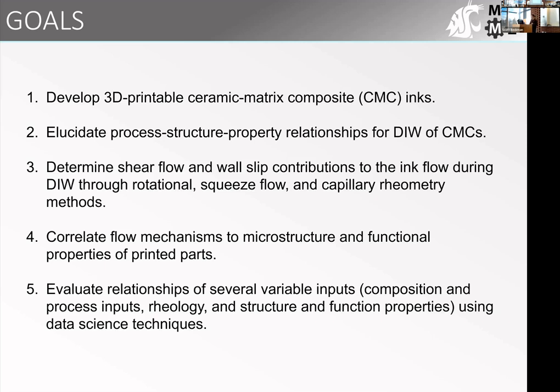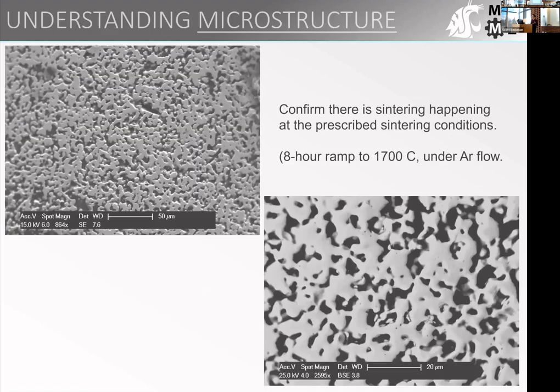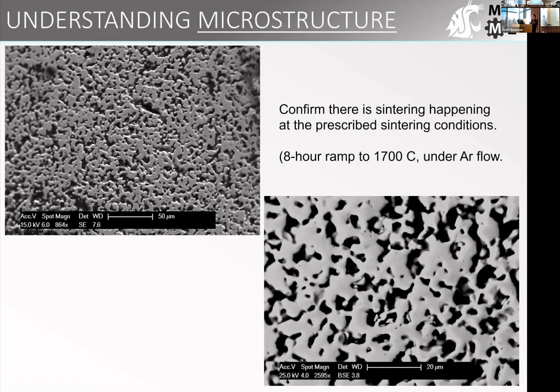So now to get into some of my results, one of the first things we wanted to do before beginning to look at the flow was just to kind of see what we're working with. So we wanted to look at the microstructure of our part and make sure that sintering was happening at the sintering conditions that we were giving it. So we were doing pressureless sintering under argon flow with an 8-hour dwell at 1700 degrees Celsius. And we saw that there was sintering happening.